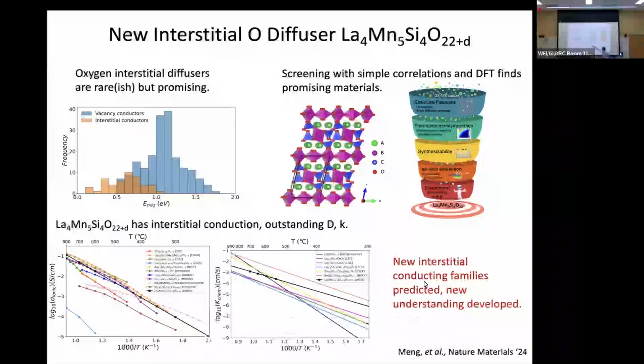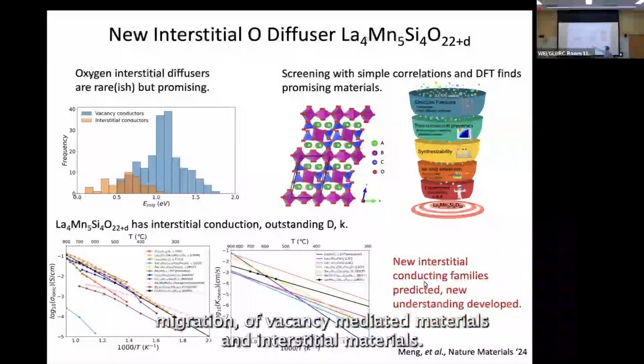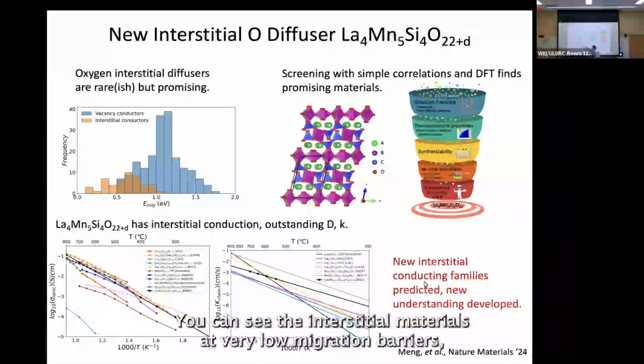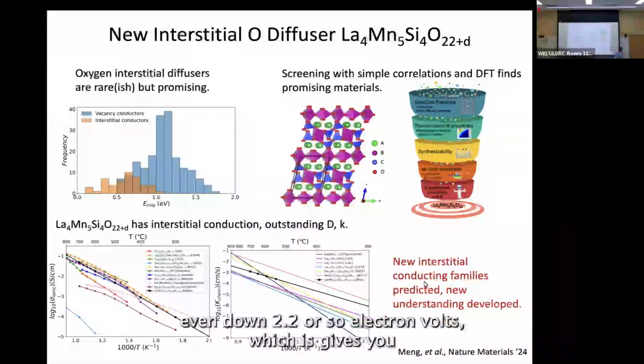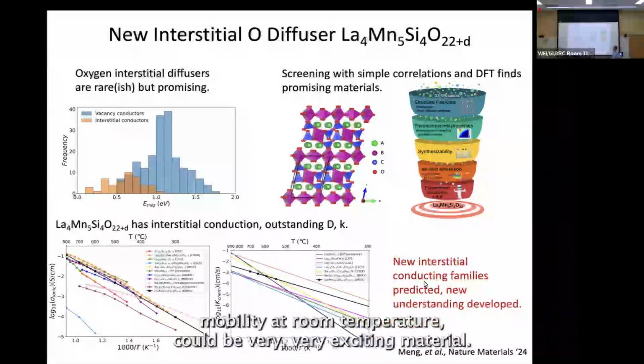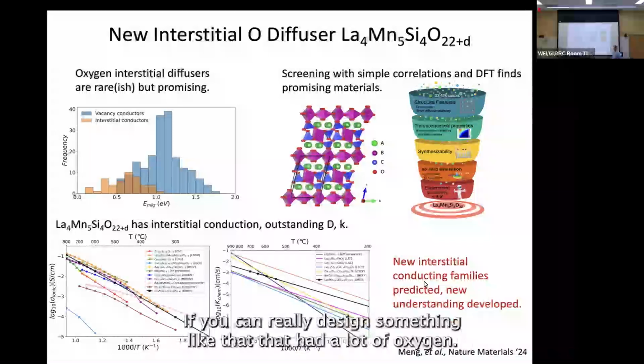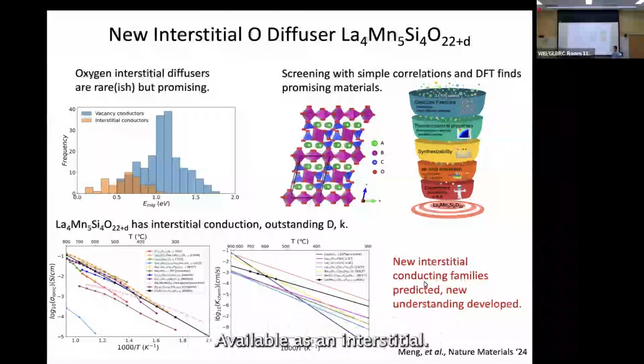These are the energies of migration of vacancy-mediated materials and interstitial materials from the literature. You can see the interstitial materials have very low migration barriers, even down to 0.2 or so electron volts, which gives you mobility at room temperature. It could be a very exciting material if you could really design something like that that had a lot of oxygen available as an interstitial. So we thought, could we discover interstitial diffusers?